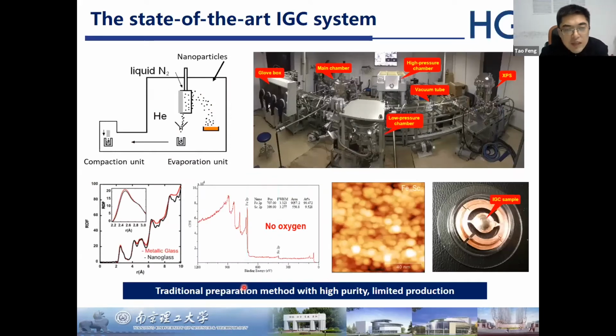The traditional preparation method for nanoglass is the so-called IGC, which means inert gas condensation. The principle is like this: we evaporate the alloy in a high vacuum system filled with inert gas. The evaporated atoms cluster with the inert gas and condense into amorphous nanograins. This powder we can collect and compact in situ into bulk materials. In our lab, we have set up a state-of-the-art IGC system, and based on it, we can prepare high purity nanoglass without oxygen inside, as fully dense bulk material.